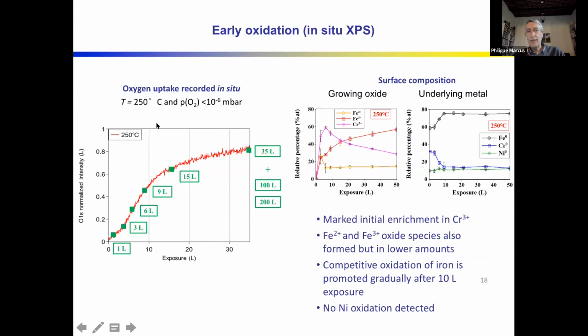And this was done in that case at 250 degrees in low oxygen pressure so that we have time to follow the phenomena. And this can be done in the XPS, and we can measure the oxygen signals while the material is being oxidized. So we can look at exposures that are very low. Just a reminder, 1 Langmuir is an exposure that is 1 second at 10 to minus 6 millibar of pressure. That's the Langmuir unit.